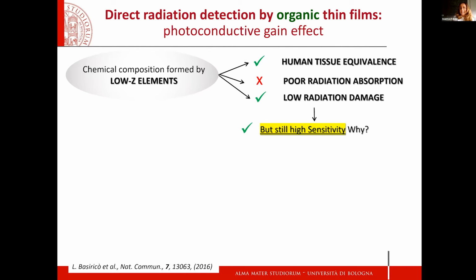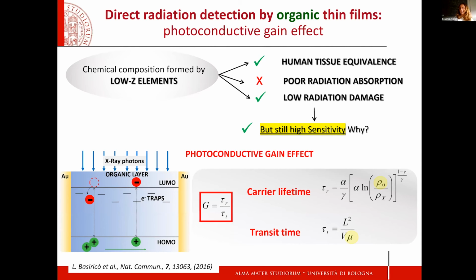Second, it does indeed absorb very little radiation, but on the good side, it has a very strong radiation tolerance. So the radiation damage is very low because really very little energy is deposited in the material. So why is it sensing and detecting radiation at all? Well, what sets in is a photoconductive gain effect that consists basically in the selective trapping of one of the two charge carriers produced by the impinging high energy photons.